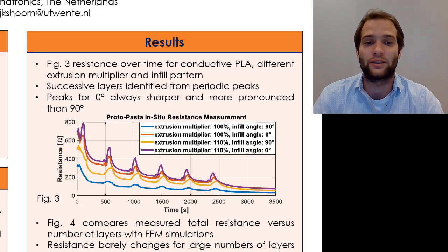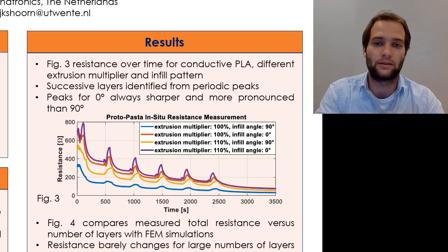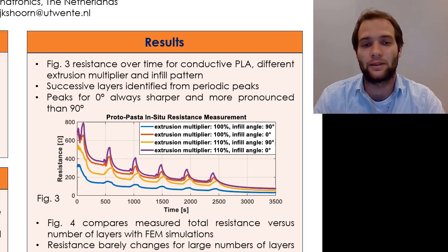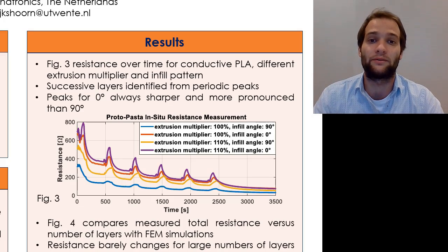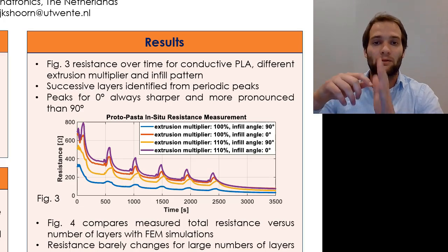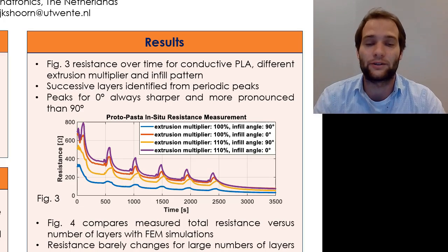For the results, you can see in figure 3 the resistance over time for conductive PLA for different print settings. And you can clearly identify the different added layers by means of the periodic peaks with the heating up and the cooling down of the sample. The peaks for the different infills give a different result. So printing parallel to the electrodes gives sharper, more pronounced peaks than printing perpendicular to the electrodes.